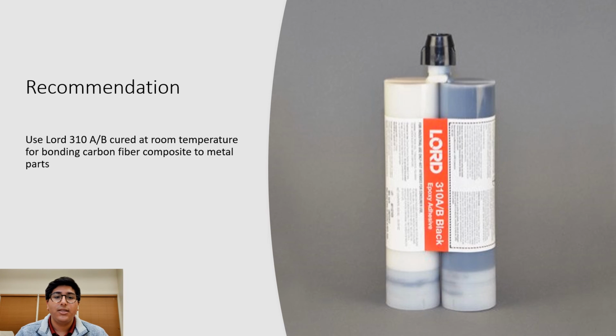My final conclusion for the team is that they should use the LORD 310 epoxy, mostly because it is readily available on McMaster-Carr at a relatively low cost when compared to other adhesive epoxies. Based on this though, I will still warn the team that there are a number of manufacturing inconsistencies that can lead to varying strengths of the bonds, and therefore all parts should be tested statically prior to driving to ensure the safety of all drivers, and that a component critical to the maneuverability and handling of the car does not fail prior to them driving.